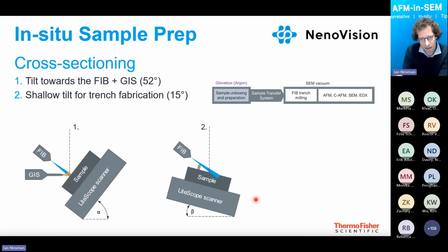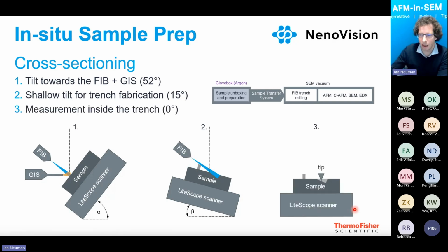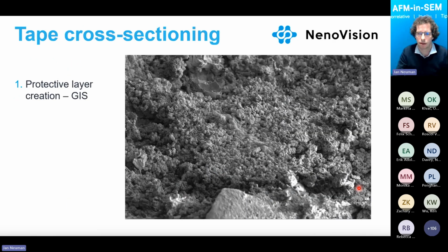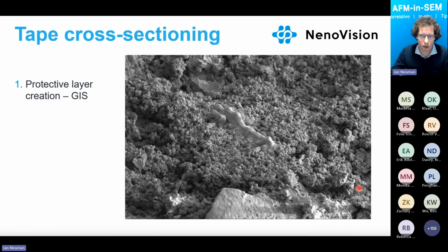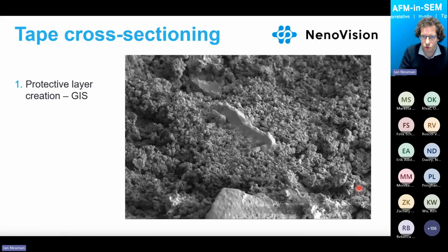Then, under the angle of 15 degrees, you can use a focus ion beam to prepare the cross-section on the sample. And then in the last step, you can approach with the AFM tip and directly analyze the area of interest. So all of that is done inside the SEM. We have a visualization of that. So you see now how the protective layer is growing.